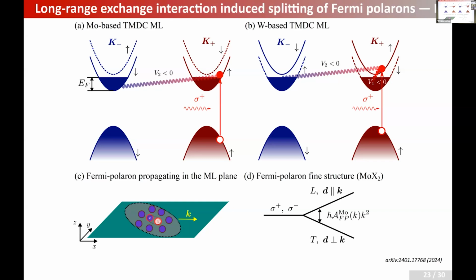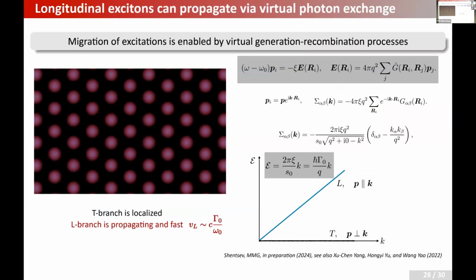In the picture of that localized exciton in the moiré lattice, the potential well is like a harmonic oscillator. So do you expect the degrees of freedom, like multiple levels inside of this harmonic oscillator potential well, to enter the story? In principle, yes. Our model is, of course, a very simple one. We consider only the ground state of this harmonic oscillator trap. Actually, the higher states have small oscillator strength, at least in theory. That is why, probably, in terms of this splitting and this linear part of the dispersion, it is sufficient to account for the ground states only. But, well, in principle, you are right. There are excited states, and they can affect the dispersion. There could be some anti-crossings here. You are right.